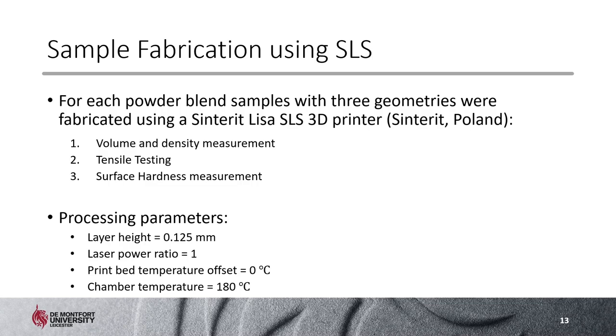After characterizing the flowability of the powders using the FT4 powder rheometer, each blend was used to 3D print and fabricate a number of samples. In total, three geometries were fabricated: the first for volume and density measurement, the second for tensile testing, and the third for measuring surface hardness. These components were fabricated using a Sinterit SLS 3D printer with a 0.125 mm layer height, power ratio set to one, bed temperature offset at zero degrees Celsius, and chamber temperature increased to 180°C before sintering initiated.